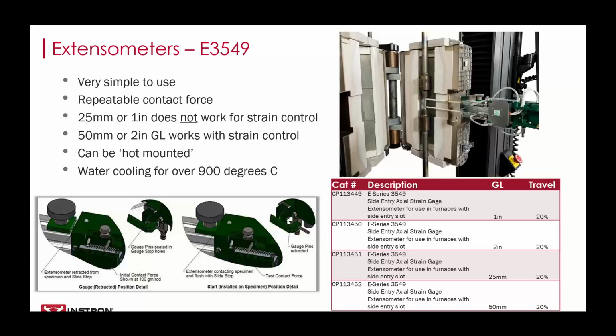With the improved stabilization that comes with the rigid mounting, this is not only easier to use test after test, but it also controls well enough to perform both ISO 6892-2 and ASTM E21 strain control testing for specimens with a 50 millimeter gauge length. This extensometer also comes with water cooling, which is recommended for testing over 900 degrees Celsius.